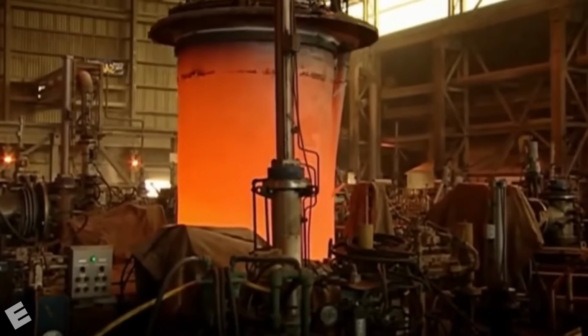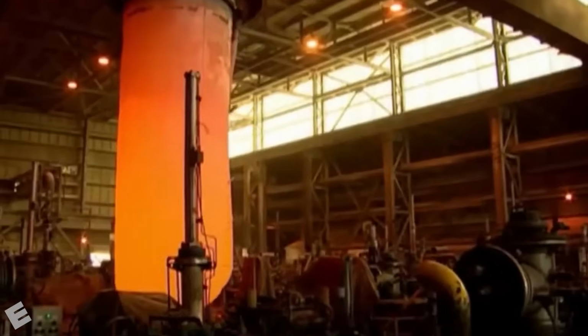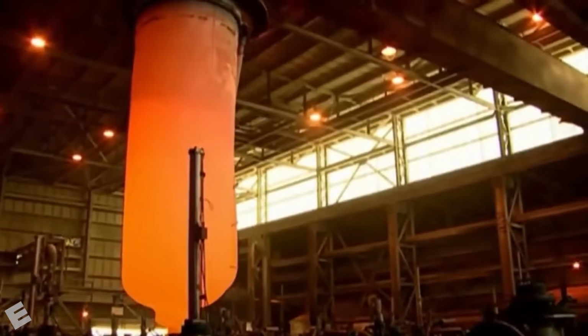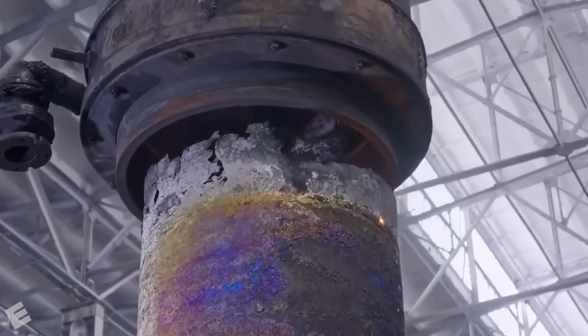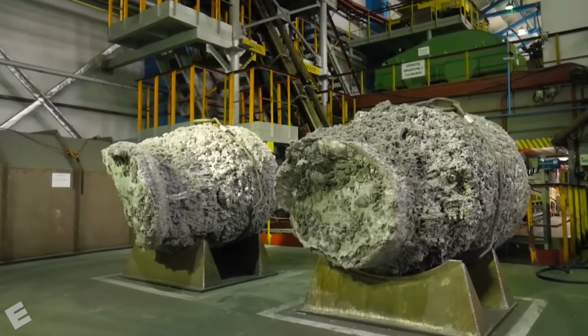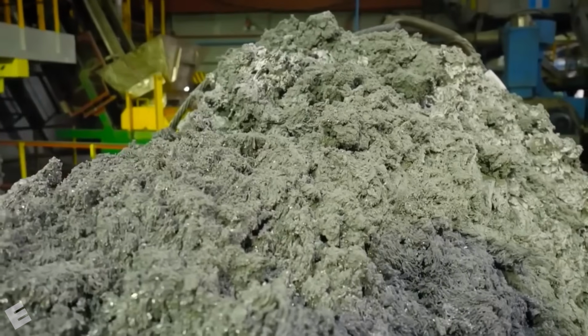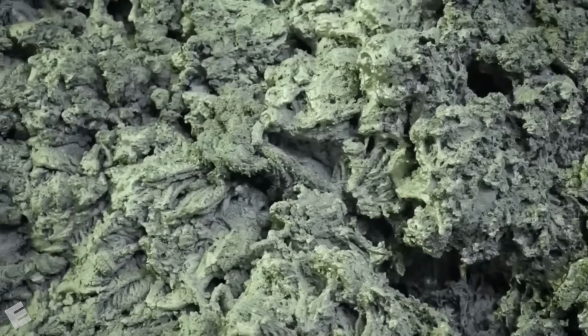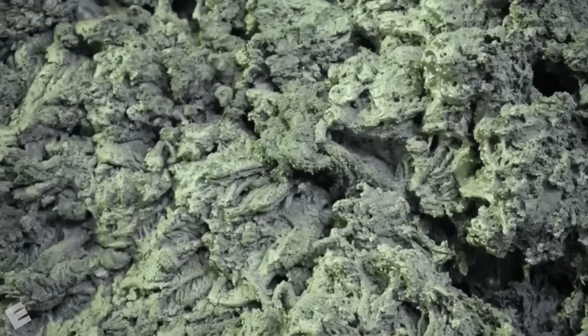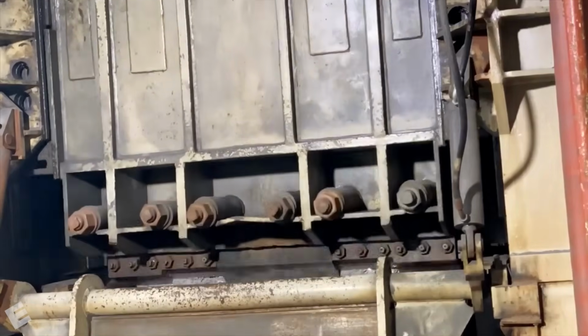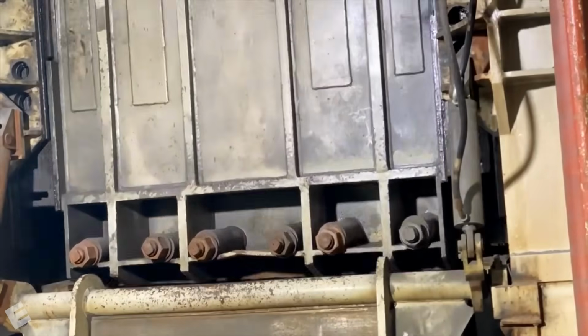Once the reaction is complete, the reactor is transferred to another furnace. A high-temperature vacuum removes the remaining magnesium, magnesium chloride, and other chemical residue. What remains inside is nearly pure titanium, but it does not yet resemble the smooth, polished metal used in airplanes. It has an extremely porous structure filled with microscopic cavities. Because of its appearance, this material is known as titanium sponge.